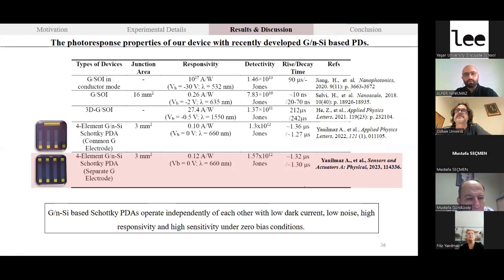When compared with the photoresponse properties in the literature, here you can see different studies related to the graphene and silicon-on-insulator case. Under the unbiased condition, our self-powered devices, even with the lowest active area compared with this literature, show excellent performance, and our devices operated independently of each other with low dark current, low noise, relatively high responsivity, and high sensitivity under zero bias condition.